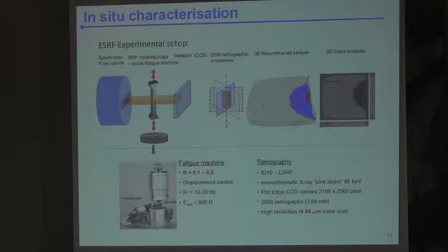In the lab, you are a bit blind to the very tip of the crack, A and B. In the lab you're using a divergent beam, so your machine or your sample has to be as near as possible to your X-ray source to keep the voxel size below 1 micron. So that's a challenge for the machine itself. In the synchrotron you use a parallel beam, so you have as much space as you want near it.